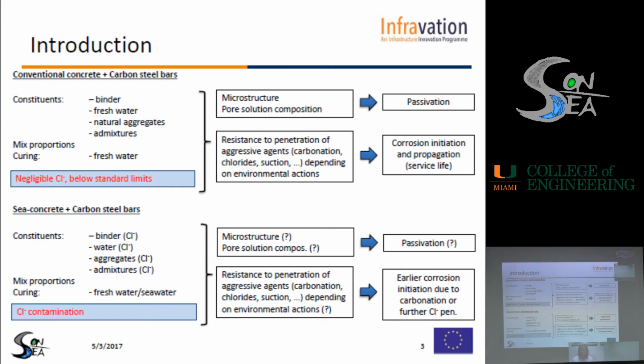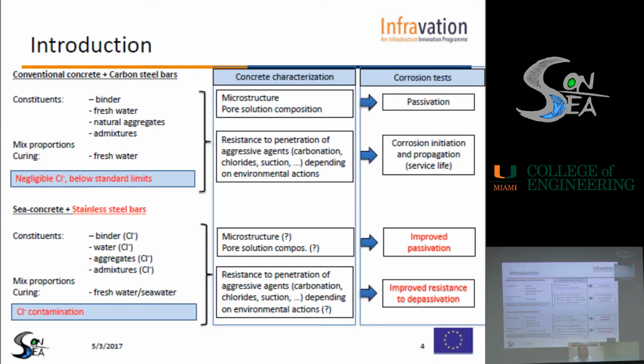It's well known that the passivation of this type of bar is improved, as well as the resistance to corrosion. So, at Politecnico di Milano, we carried out several tests in order to characterize the concrete, to study how chlorides affect the resistance to penetration of aggressive agents, as well as the microstructure and so on, and corrosion tests to investigate the corrosion behavior both of carbon steel and stainless steel bars.